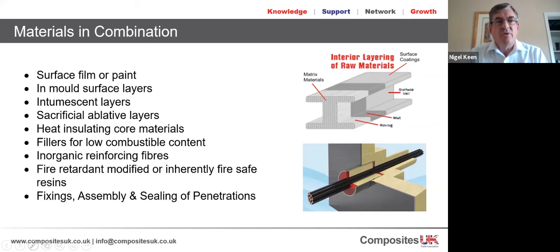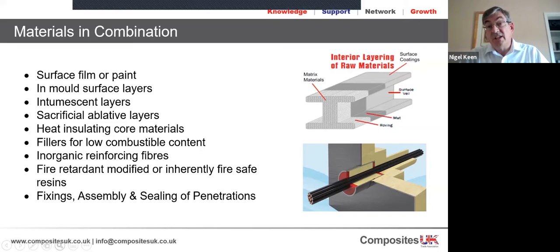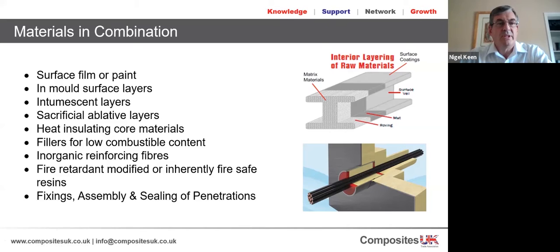So we'll build in extra layers and we'll model the amount and speed that we burn the composite away, and we allow perhaps the glass to hang and provide the structure. So you can actually have sacrificial layers that will protect the structure and keep it functional for a period, allowing escape. Core materials themselves are good insulators. Composites are good insulators of themselves, but core materials, being very lightweight, can be very good at insulation, so they can be a part of the solution. And fillers can be used within the matrix to reduce your combustible content.